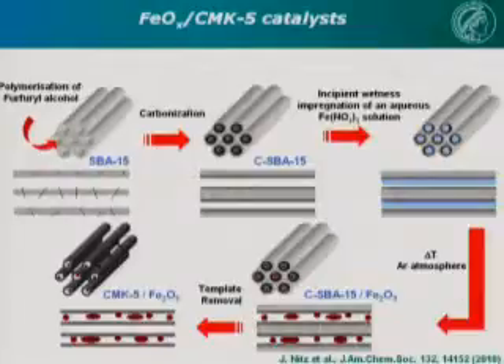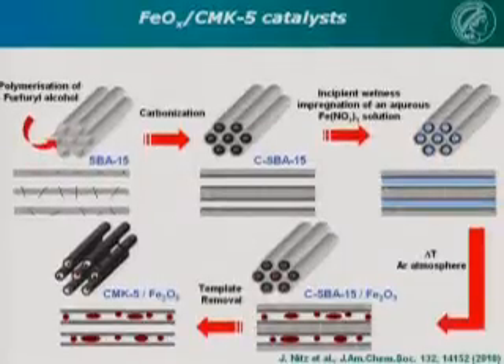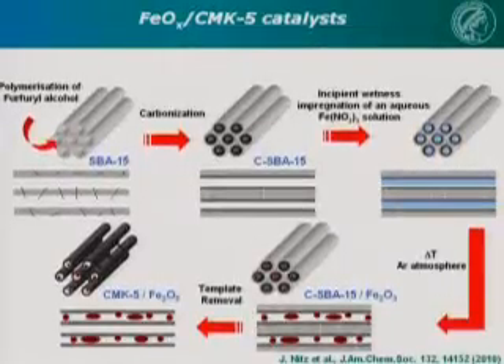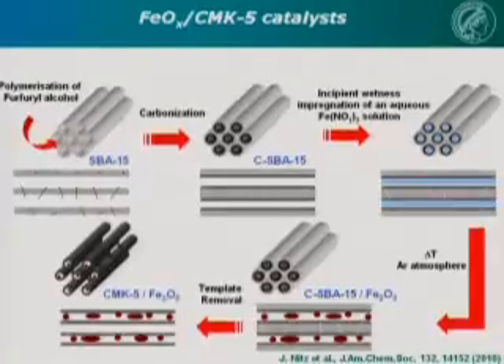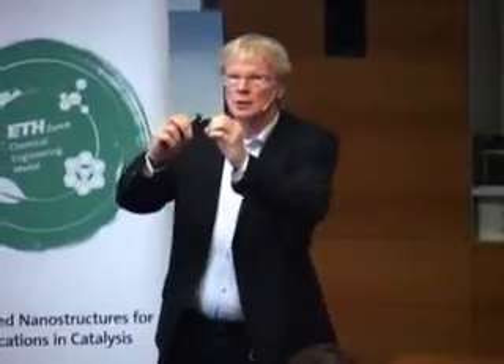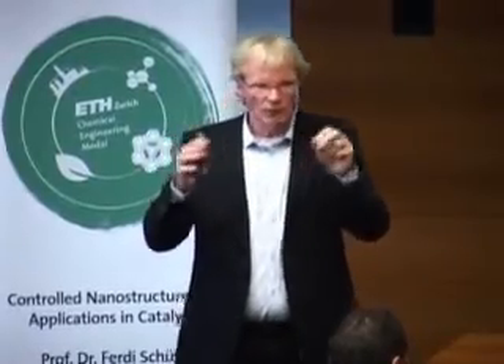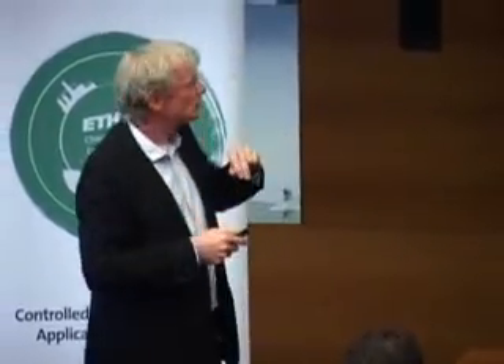Now, the way we try to produce these very small iron particles is we start with SBA-15, a hexagonally ordered porous silica where the pores are formed by basically templating from a surfactant liquid crystal, in a very superficial description.